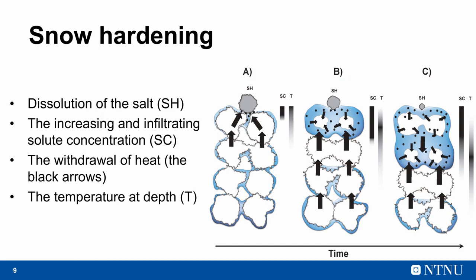So, the point here is that we assume that we have snow crystals, we assume that we have free water, that is the blue. Here we have a salt grain, and these black dots, that is the dissolved components. So, we have a solute here, and then we start melting. You see here, we start melting the snow at the top, but to melt, you need energy, and that is what you are taking from the snow around. So, you see that from below, you will get the cooling of the snow, and then suddenly, the solute will go down, you will have this melting process, but then you will start actually freezing these snow crystals at the top, that will give away energy to this process, and then you go on. So, at the top, we get a firm snow that is colder than it was, and that is the clue for us when it comes to salt hardening.